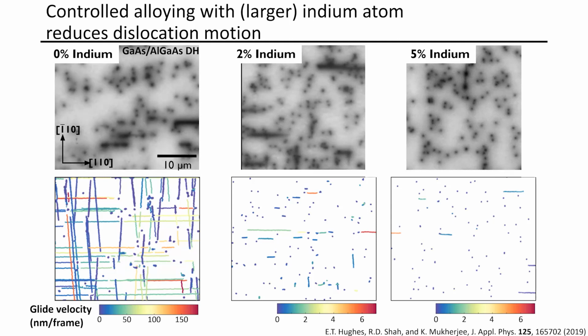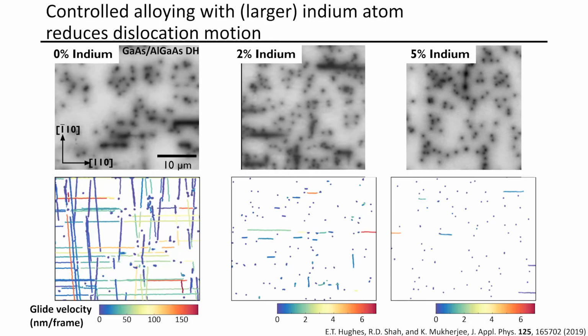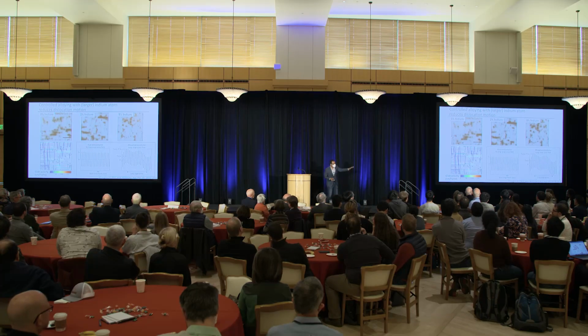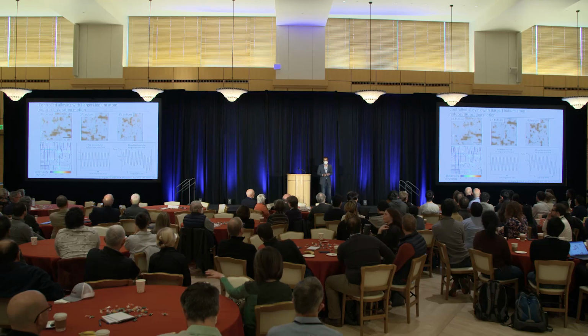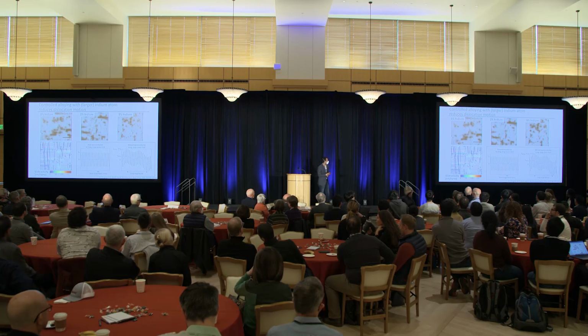For a metallurgist, this is no surprise. Of course, you start alloying differently sized elements, you get alloy hardening, right? This is reasonable. But for a semiconductor group, we're legally allowed to put in like 2 things in gallium arsenide without messing up the electronic properties. Indium luckily happened to be one of those things that we were allowed to put in. It's a significantly bigger atom, and we can, just by putting small percentages of indium, actually block the movement of the dislocations. I initially thought I was going to go into some of the details of the Peierls barriers. I was like, yeah, not today, but I'm happy to discuss this over coffee.